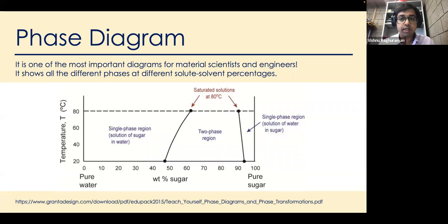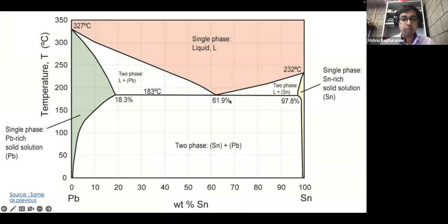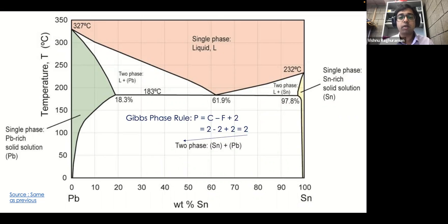So we can look at a phase diagram for a real system, which is solder, lead, and tin. So once again, you have a pure lead limit and a pure tin limit. And at small solute concentrations, you have single phase. And then at high temperature, you have single phase. But everywhere in between, you have two-phase regions. And the way you keep track of the number of phases is what's called the Gibbs phase rule. And here P refers to the number of phases. C refers to the number of components in the system. So here you have lead and you have tin.